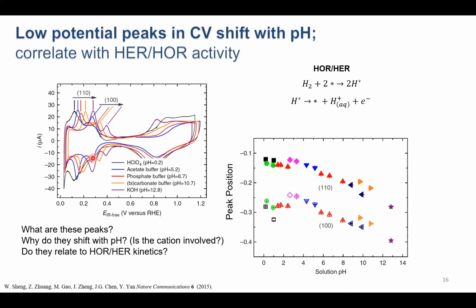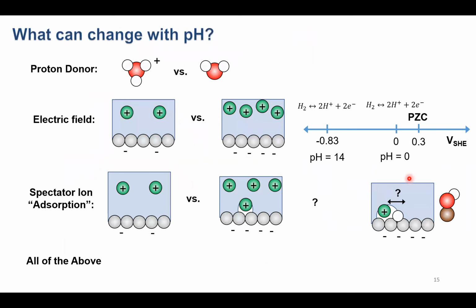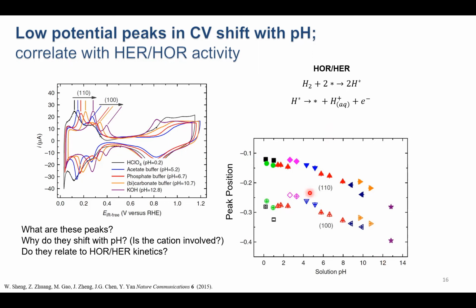And so I realize that this kind of looks like a mess here. These are CVs measured on polycrystalline platinum in electrolytes with different pH. There are two sharp peaks that are known to be seen at low potentials here. And we see that those sharp peaks shift more positively with increasing pH. And so that's highlighted in this figure on the right here. They shift roughly linearly with increasing pH. I'll mention we've already accounted for the expected thermodynamic shift we would see with pH. And so this is truly an anomalous shift beyond what we would expect from standard thermodynamics. And so we might ask, what is going on in these peaks? We know it's an adsorption reaction.